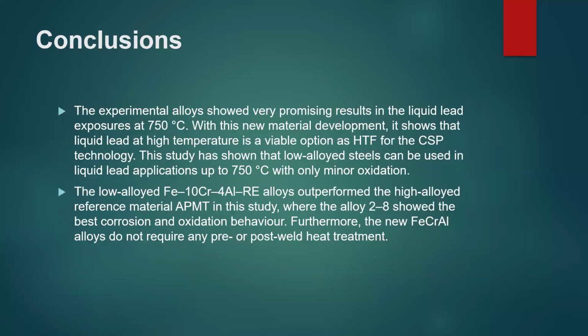For the conclusion: first, the experimental alloys showed very promising results in liquid lead, especially at 750 degrees Celsius. This new material development shows that liquid lead at high temperature is a viable option for HTF in CSP technology.